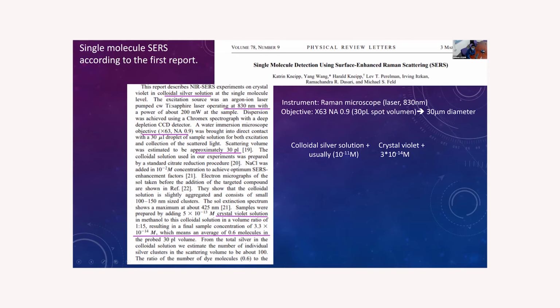They use this concentration because they want to be sure that they will have only this amount of molecules, 0.6 molecule in the scatter volume. That means that there can be two possibilities. If they don't have any signal, perhaps it means that there isn't any molecule in the volume. But this is dynamic, so at some point they will start measuring, because they are taking one spectra per second.